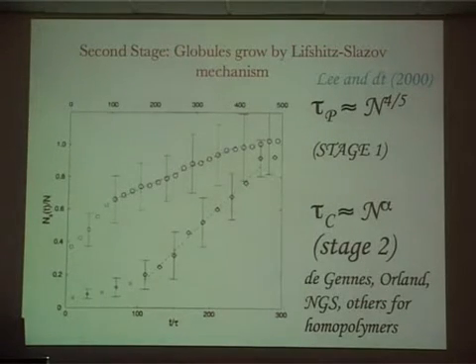But the second growth, where the big ones engulf the small ones, occurs, it turns out, by Lifshitz-Slyozov growth, with this alpha roughly about 3. So we showed this roughly speaking. So there are two stages in which collapse occurs.